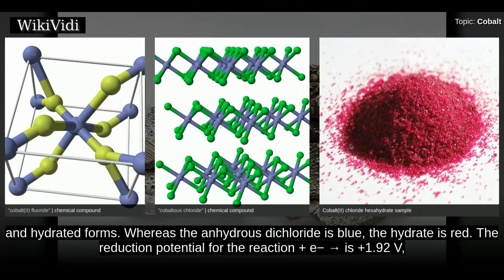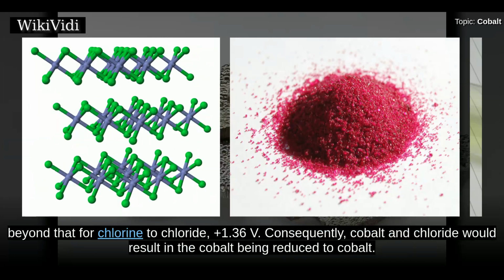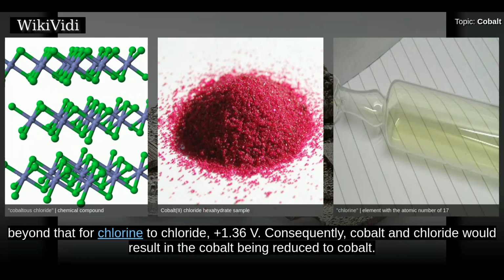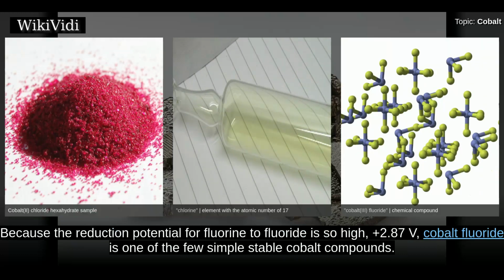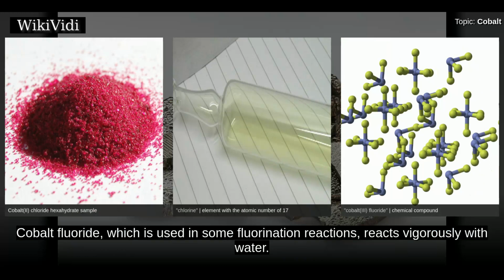The reduction potential for the reaction Co3+ plus e- is plus 1.92 V, beyond that for chlorine to chloride, plus 1.36 V. Consequently, cobalt and chloride would result in the cobalt being reduced to cobalt 2+, because the reduction potential for fluorine to fluoride is so high, plus 2.87 V. Cobalt fluoride is one of the few simple stable cobalt compounds. Cobalt fluoride, which is used in some fluorination reactions, reacts vigorously with water.